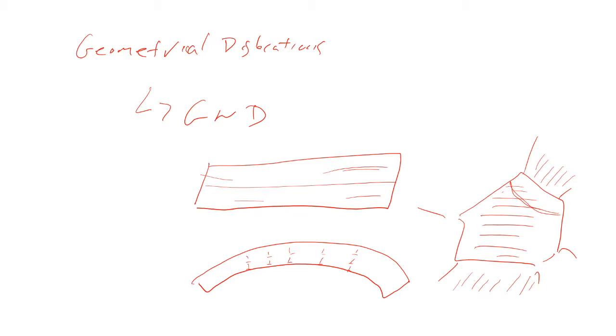Which means that the orientation of my crystal or my lattice is going to have to be curved because I have a shear gradient. And I'm going to have a gradient in my orientation across my crystal. So that means I need arrays of dislocations to keep this curvature there. And those are what people classically refer to as geometrically necessary dislocations, right? They are dislocations that support the curvature but don't have a net Burgers vector. If I do a Burgers circuit around these, because my lattice is curved in the same way that accounts for the Burgers vector of the individual dislocations, I don't have a net closure failure of my Burgers circuit.